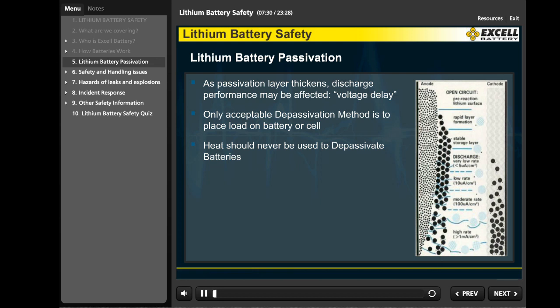The passivation layer thickens over time due to various other conditions, including prior discharge. The passivation layer acts as a high-resistance barrier between the anode and the cathode that needs to be broken down to allow efficient ion movement between the anode and the cathode. As it thickens and as the passivation layer resistance increases, the cell or battery voltage will initially drop to a very low level before recovering to a stable voltage. This is called voltage delay. The voltage recovery is a result of the passivation layer resistance breaking down, and this action is known as depassivation.